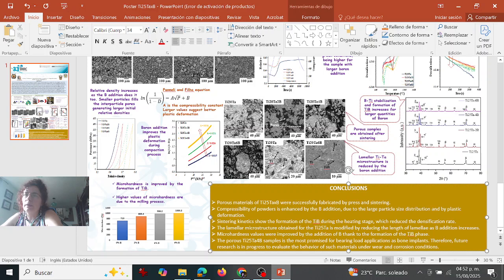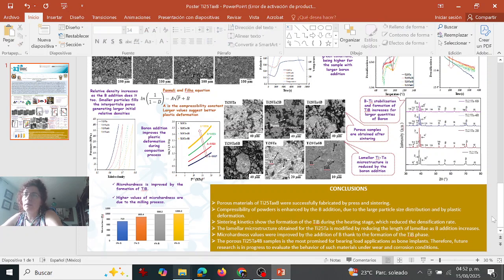So the porous materials of titanium 25% tantalum with boron were successfully fabricated by press and sintering. The compressibility of powders was enhanced by the boron addition, and this is due to the large particle size distribution and also to plastic deformation. The sintering kinetics showed that the formation of titanium boride during the heating stage reduces the densification rate. Also, the lamellar microstructure obtained for the titanium 25% tantalum was modified, reducing the length of lamellae as boron addition was increased.